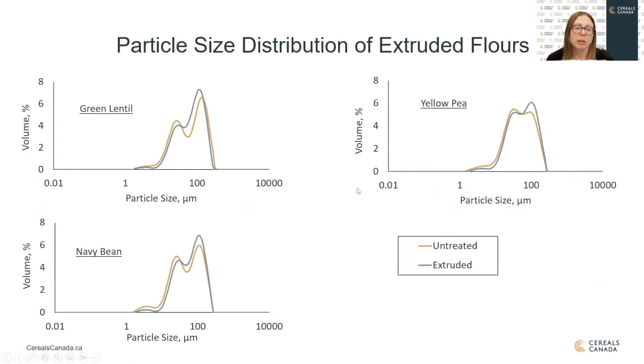So the particle size distribution between these two flour treatments didn't change too much. The extruded flours did have slightly more large particles, likely due to that clumping that then needed to get remilled. And again, that remilling shrunk the span of the distribution, so the flours were more consistent with the extruded treatment.